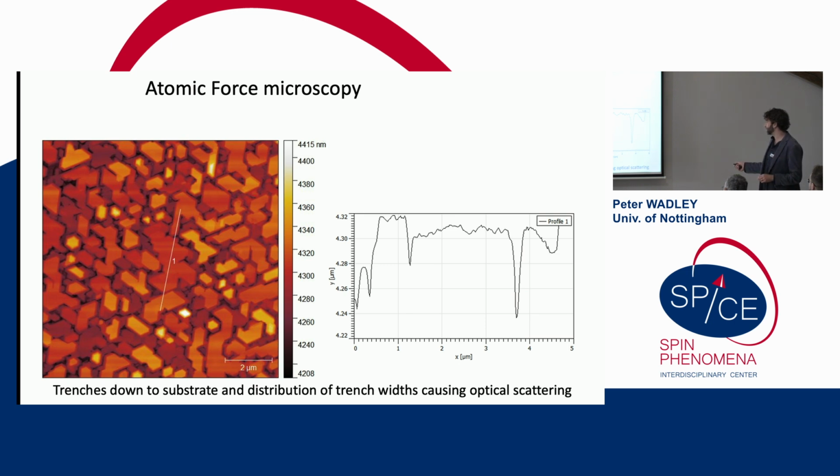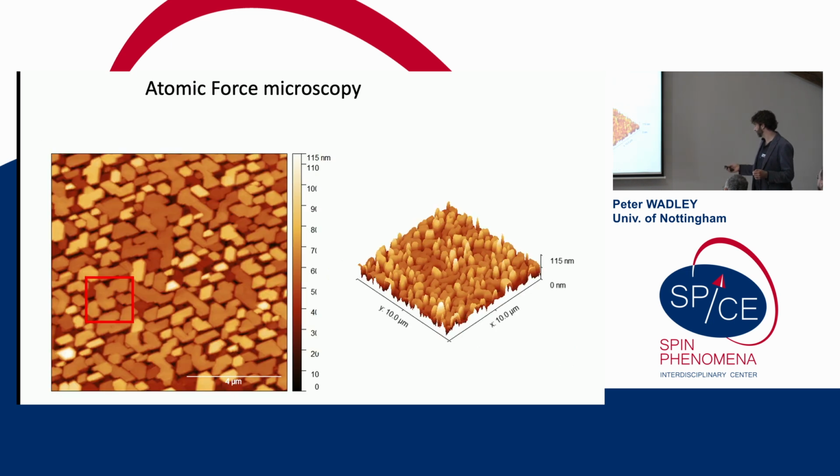If we look in a bit more detail, wider out at the atomic force microscopy, you can see that you have these flat-top mesas with slightly varying heights. These trenches actually go right the way down to the substrate, so they're inherent in the buffer layer as well. More nice pictures of these hexagonal structures.